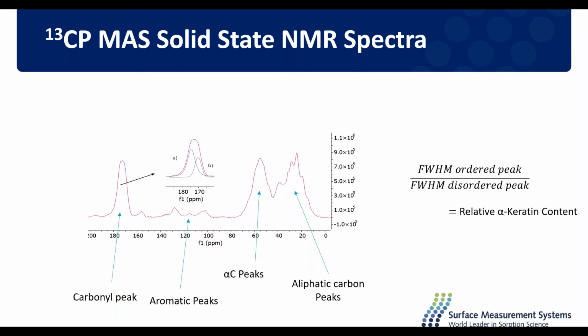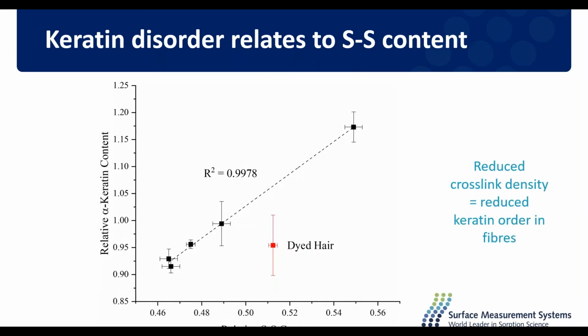And if we plot that relative order against that crosslink content, we can see a really nice correlation. With increasing disulfide bond content, there is more order in the samples, and with the decreasing disulfide bond content, we get reduced order. However, we do see one particular glaring outlier, and that's the dyed hair. So it has a reasonably high crosslink content, but quite a low relative alpha keratin content. So why is that?